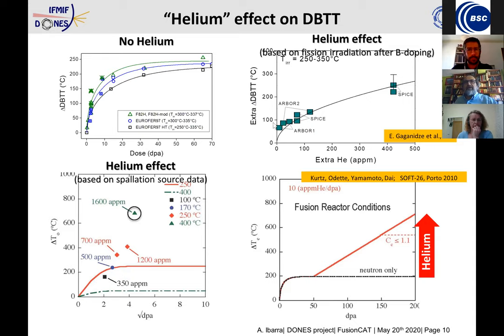In both cases, you can see that there is an additional shift of the brittle to ductile transition, additional to the one that we get with fission. This additional shift can be more than a few hundred degrees centigrade. So with the present understanding that we have today, this is the figure in the lower right part, we have the impression that if we work in a fusion reactor in which we will have helium and DPA, the shift of the ductile to brittle transition can be hundreds of degrees centigrade.